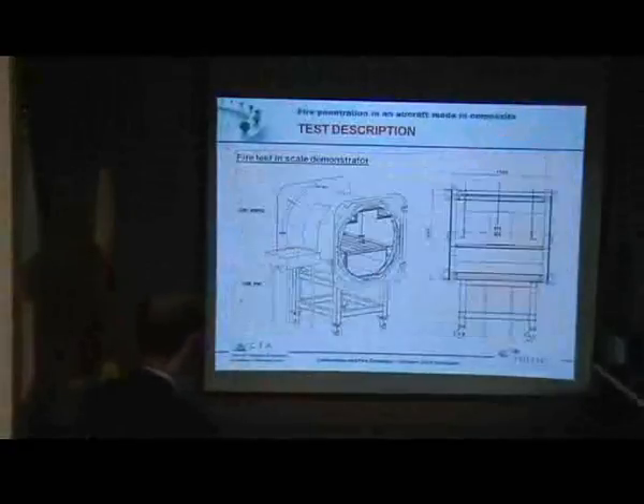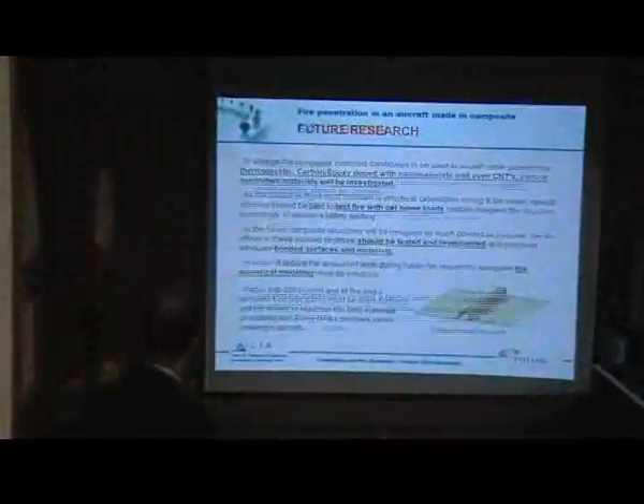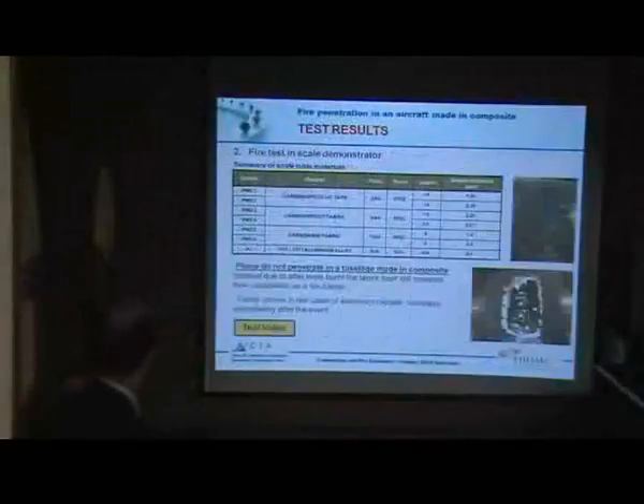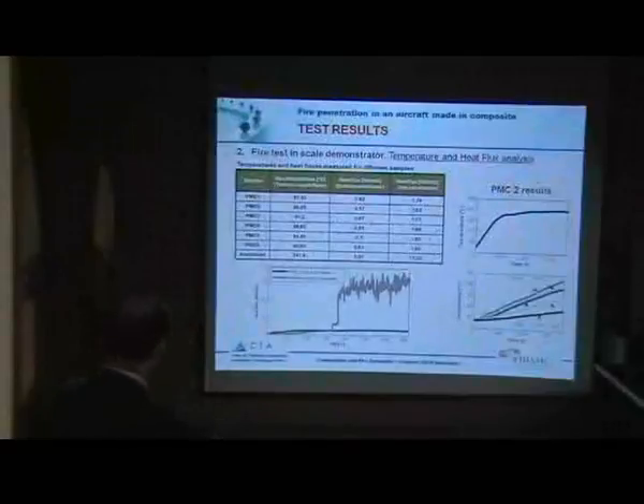So we're going to see now the main measurements and results we have during this test. Here you can see the maximum temperature that we measure with the thermocouple 3 inside the cabin, so we reach around 90 degrees. With the aluminum fuselage, once the flame penetrates, you can see how there is an important increase in the temperature. This is the temperature in the cold surface of the composite materials. We have around 400 degrees in the cold surface of these materials, and this is the temperature distribution in the thermocouple 3 inside the cabin.